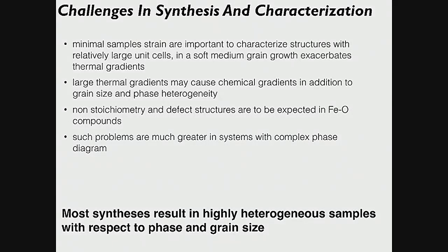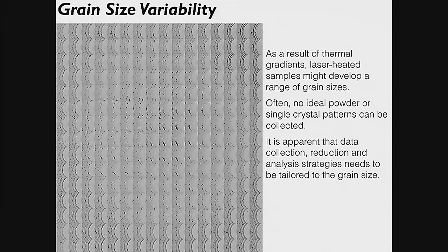complex. You want to have the minimal strain. You need to know that your thermal gradients cause some phase changes, some chemistry, and some chemical gradients. So what do I do with this sort of sample? Well, I use a very small beam, and I collect space-resolved images. I map out the sample.